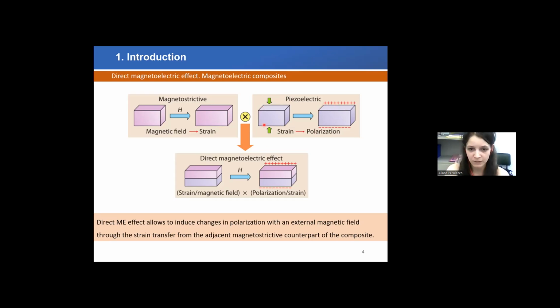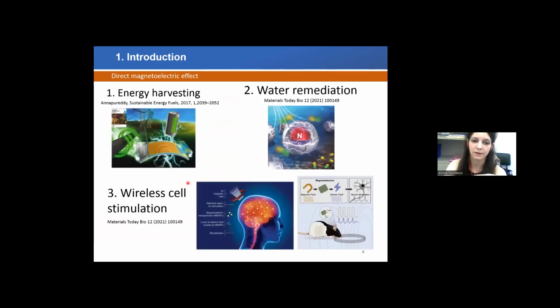So when these two phases are coupled together, we can produce a composite material where the external magnetic field will generate strain in the magnetostrictive part. This strain will be transferred to the piezoelectric part at the interface, and this material will generate charges. So like this, we can modulate the electric polarization of a composite material by applying an external magnetic field. These kinds of composite materials have found applications recently in three different areas.